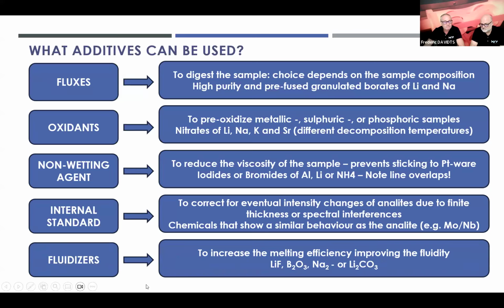Fluidizers are the last additive we speak about, and fluidizers are used to increase the melting efficiency and to improve the fluidity, so to cast it easier also. So lithium fluoride, boron oxide, sodium or lithium carbonate are therefore used. And the fluxes we will later on look at in more detail with Frederik.